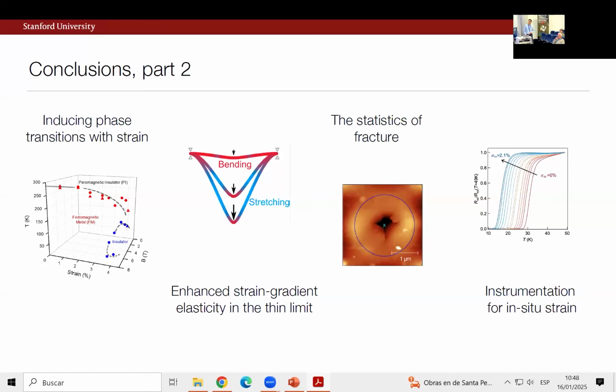Let me close and just say, in this second part, I tried to tell you about our first generation efforts to use strain to induce phase transitions. So this is a figure from the manganites. I told you a little bit about how these nanomechanical probes have really revealed interesting and dominant contributions from strain gradient terms, especially because the scaling with thickness is so favorable.